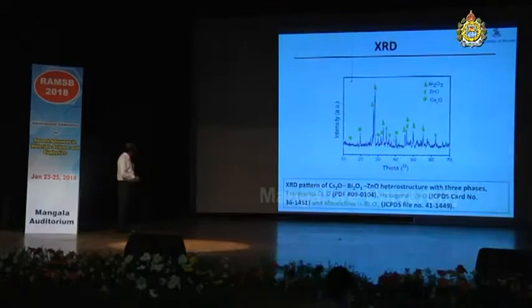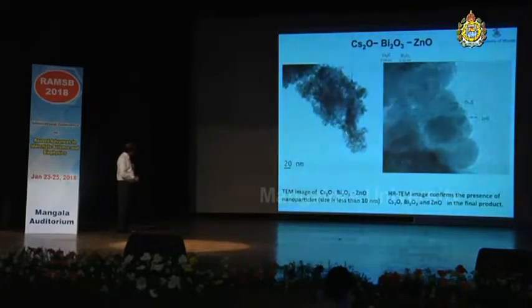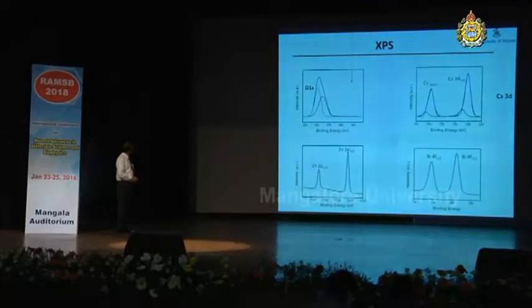The same image when we subjected to the TEM analysis, we could understand that the size is less than 10 nanometers, maybe in the range of 5 to 6 nanometers. And here, the high resolution image confirms the presence of all the three compounds, oxides of zinc, cesium, and bismuth, and also the d spacings are given. This is how the product looks so fine,